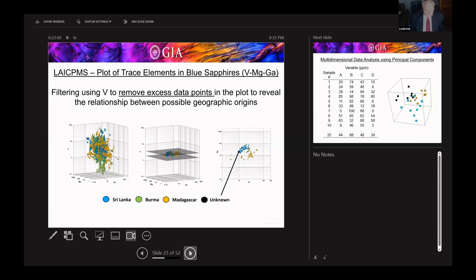On the left, this is again blue sapphire analyses in terms of gallium and magnesium on the horizontal two-dimensional graph, and vanadium on the vertical axis. The unknown, we know where it is because we just analyzed it. It's in that mass of colored data points in the left-hand graph. One technique we're using is to filter out excess data points that are far removed from the location of the unknown. When we do that, we strip out all these excess data points, which are far away chemically. Now you end up getting a much simpler plot on the right-hand side and a much more likely chance of saying, in this case, this blue sapphire is from Sri Lanka in terms of chemistry.